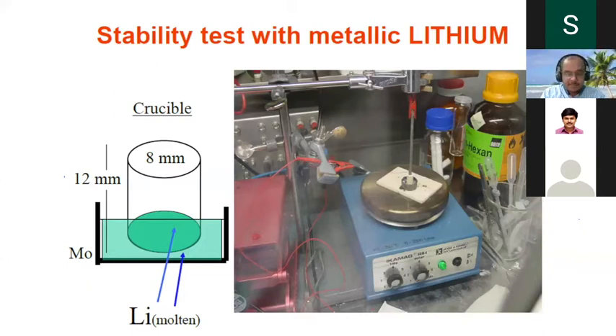Very interestingly, except tantalum. Tantalum doesn't react with the molten lithium, there is nothing. But when I put the antimonide substituted samples, within a fraction of a minute, black dots start to appear, which tells me that the surface starts to react with metallic lithium. Niobium is completely black. But very interestingly, the maximum conductivity I got was from the bismuth doped samples.